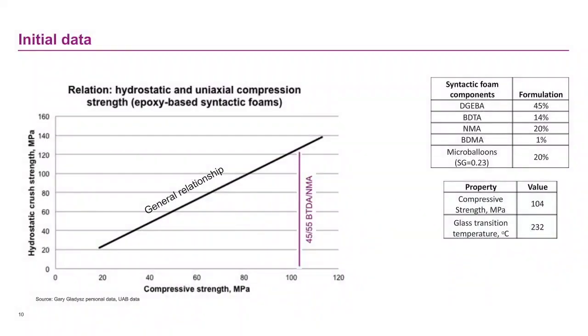Here's an example of some of the data which is starting to come in from the study. You've got hydrostatic crush strength as a function of uniaxial compressive strength, something that can be easily measured in the laboratory, against something that would be more indicative of material in service. And there's a clear relationship between the two. One mix which we formulated gave us a compressive strength of 104 megapascal, which correlates to about 120 megapascal of hydrostatic crush strength. So those are very impressive numbers.